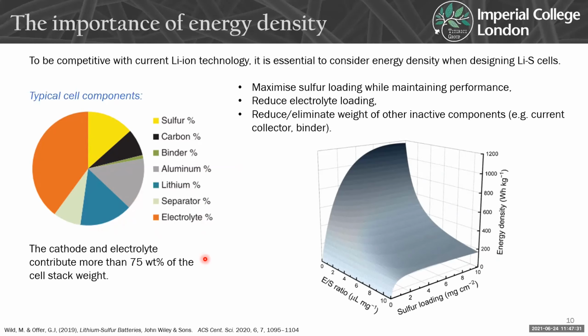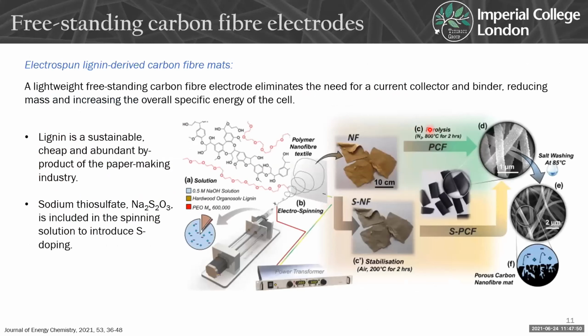So if we want to increase the overall energy density, what we want is to increase the amount of the active material, so that's the sulfur loading inside the cell. And basically we want to then reduce the mass of everything else inside the cell, so that's the electrolyte and the current collector and the binder, if we can. One good approach to doing that is to try to create freestanding electrodes. If we can have a freestanding electrode, it means that we don't need the current collector and we don't need the binder.